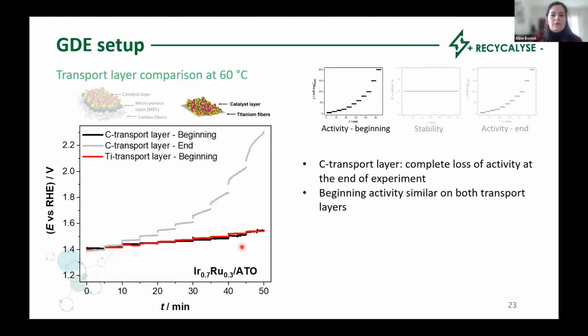Then moving forward to the titanium-based electrode, we see that the beginning activity, so the red curves, are in line with the black ones. This means that both electrodes give similar activity, which is expected as the same catalyst is used, and the transport layer should have a minor effect on the overall activity.